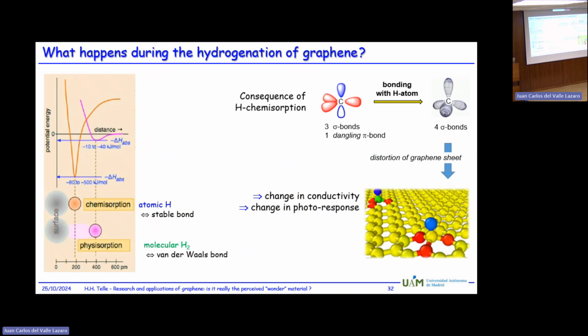Nevertheless, it works. The second thing I want to demonstrate here is, if we go a little bit more into the detail, how to actually bind hydrogen to the graphene. If you simply take your graphene and add a little bit of hydrogen, so you are in the gaseous atmosphere, nothing really happens. Basically, you only have van der Waals bonds of hydrogen molecules on top of the graphene. And the binding energy is so small that even at room temperature, once you take the hydrogen away, everything is gone again. So you need to actually do chemisorption, so build a proper bond so that you have hydrogen atoms which bond to the system.